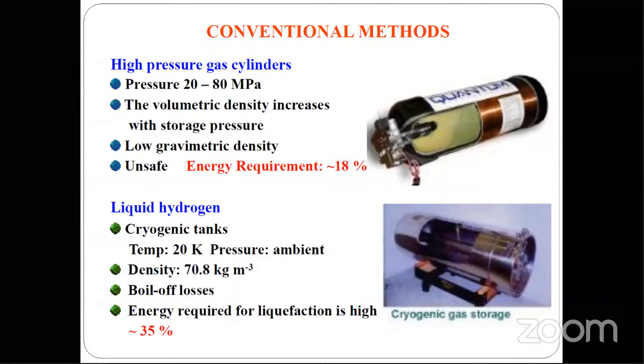Then if you go for liquid hydrogen, the second option, as you know, hydrogen can be liquefied at 20 Kelvin at ambient pressure. You have to go to a very low temperature to liquefy the hydrogen. The density at 20 Kelvin is huge, that is 70 kg per cubic meter. So it's a very good density to have for transport applications.